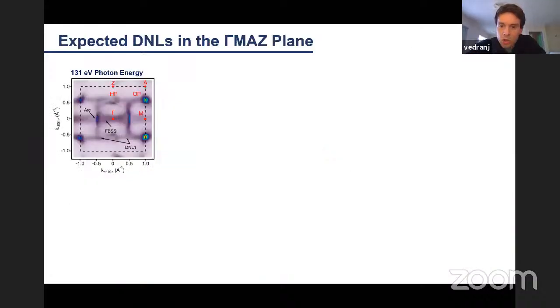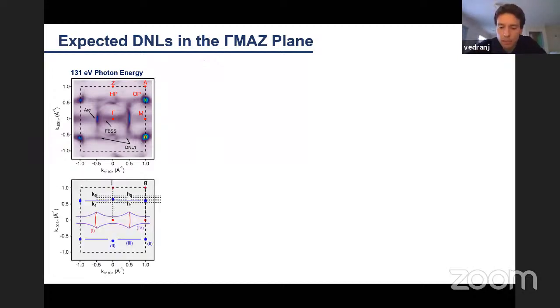So to confirm this theoretical scenario, which was predicted on the previous slide, let's take a look at the Fermi surface collected at 131 electron volts. So with the direct lattice parameters that I've indicated here, the black dashed line shows the primitive Brillouin zone markings, and we can identify four main contributions to the Fermi surface. I've summarized these in this little schematic here on the bottom left using the numbers 1 to 4.